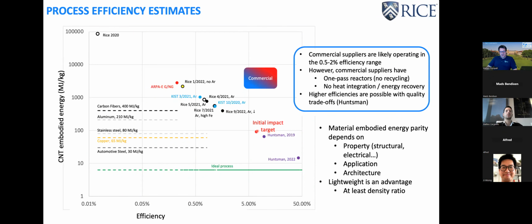megajoules per kilo. So at this point, we would be levelized with some of the high-end steels, aluminum, and carbon fibers. Now, Huntsman, which has also been funded by ARPA here, can now go and make this material in a very efficient way, but they lost properties. And so now there is also a question of whether Huntsman can walk back up this line, give up a little bit of efficiency, and still recover the properties. But the bottom line, one does not have to go to very high efficiencies to have an effect. If one can get a 5 to 10% reaction efficiency, this route becomes very interesting.